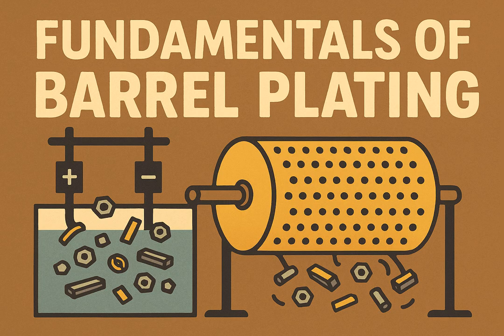Peeling. Nightmare scenario. Definitely. Peeling can also be caused by interruptions in the electrical current during plating, or if the bath temperature is too low for the specific chemistry. The sources offer a key diagnostic tip: examine the underside of the peeled layer and the exposed surface beneath it. Like playing detective. Kind of. If you see the bare base metal, the problem likely occurred during initial surface preparation or the very first plating step, like a strike layer. If you see an intermediate plating layer, like a copper strike, then the issue happened between that step and the final plating layer. So the layer tells you when it failed. Exactly. Maybe poor rinsing or an improper dip between baths caused it at that stage.